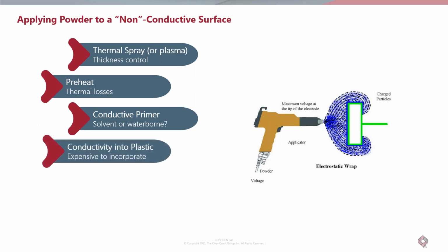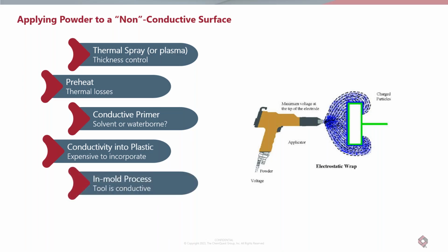The other thing you can do is put conductivity into the non-conductive species. This can be done with something as simple as a conductive carbon black pigment, so the part becomes any color you like as long as it's black. You can use lower concentrations of something like carbon nanotubes, but that makes the overall material cost rather expensive.